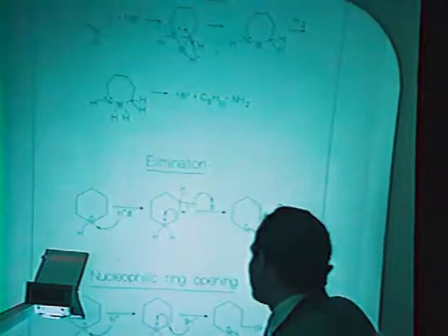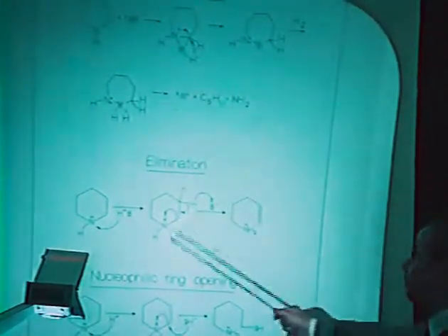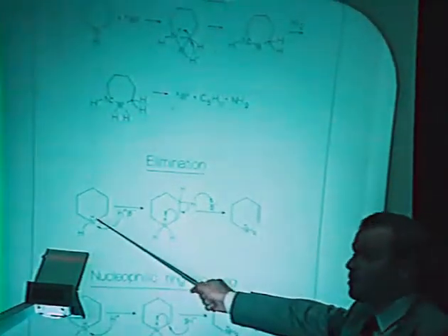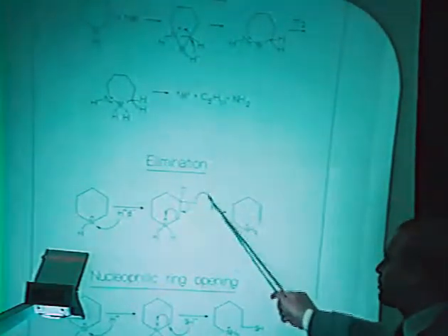That could help us in determining whether this elimination mechanism is possible. So we see that when piperidine interacts with the ODs of the surface, the beta proton of the piperidine is labile, and that is shown by the exchange. So this shows at the same time that the elimination mechanism is a feasible mechanism for the hydrodenitrogenation and for the carbon-nitrogen bond scission.